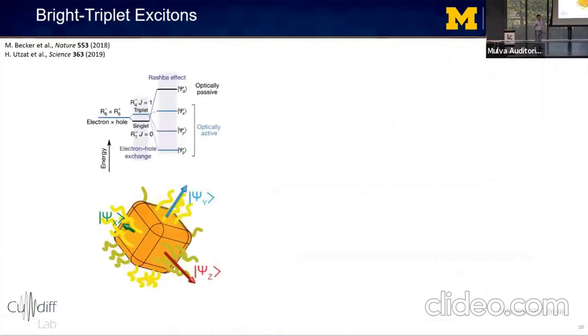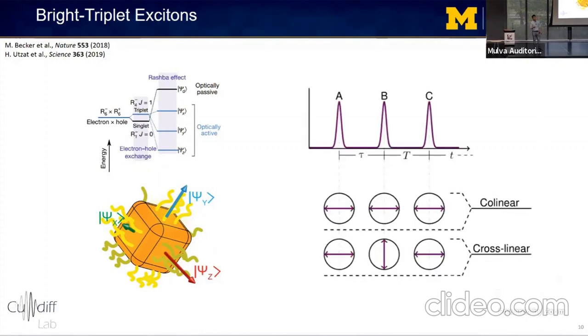So one of the most useful properties of these bright triplet states that I haven't mentioned yet is that their dipole moments point in orthogonal directions. So to measure quantum pathways involving these triplet states, we vary the polarization of our second excitation pulse, which in this diagram is pulse B. And below the pulse diagram, you can see the relative polarizations of each excitation pulse in the laboratory frame. And we call the first polarization scheme collinear polarization and the second one cross-linear polarization.